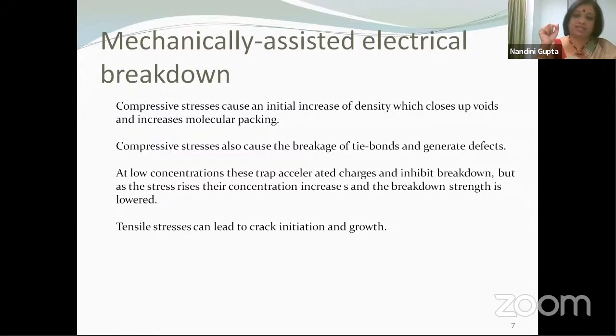Whereas compressive stresses can cause an initial increase in density, so initially it's a good thing to happen, but over time that's not going to continue. And after that, what will happen is compressive stresses will cause breakage of tie bonds and will generate defects. And that's a problem because defects tend to trap charges. Now, what do I mean by trapping of charges? When I have a material which is stressed electrically, there would be injection of charged particles into the material. When there is injection of charged particles, these charged particles move through the material and cause mobile conduction, and therefore they cause some kind of losses due to current flow, small current flow. But at the same time, a second thing can happen, which we will be discussing in detail, I think, day after tomorrow, that is trap formation can happen.